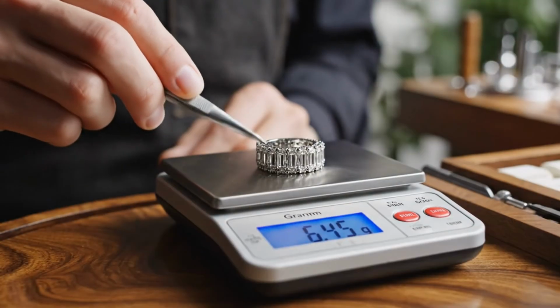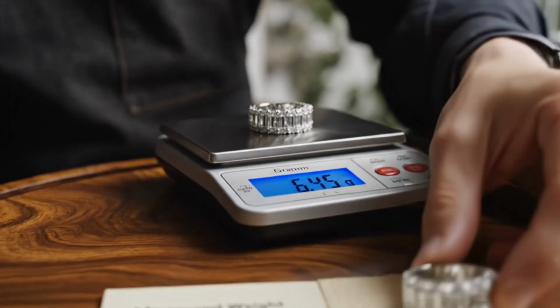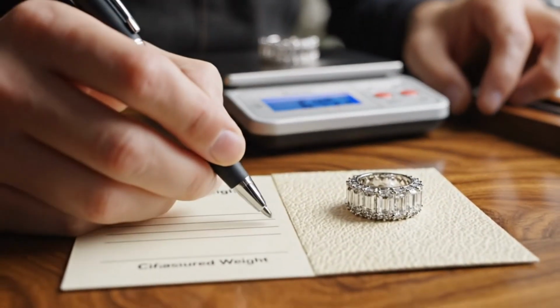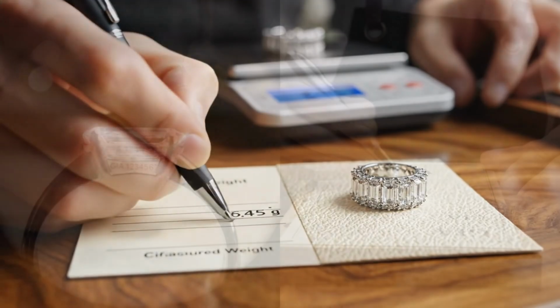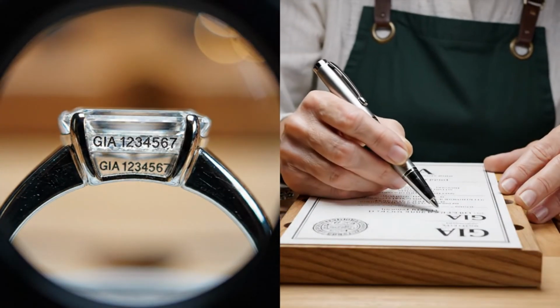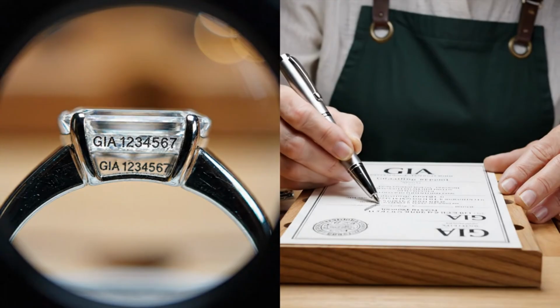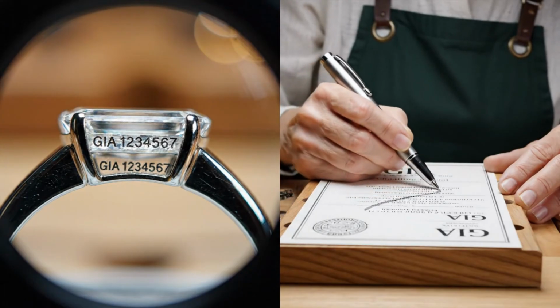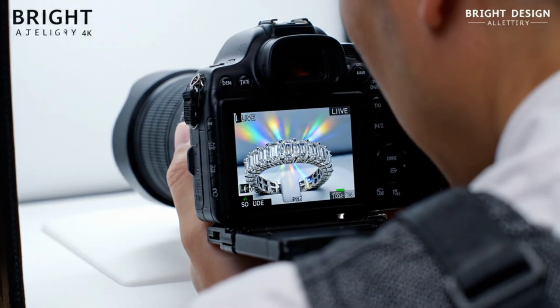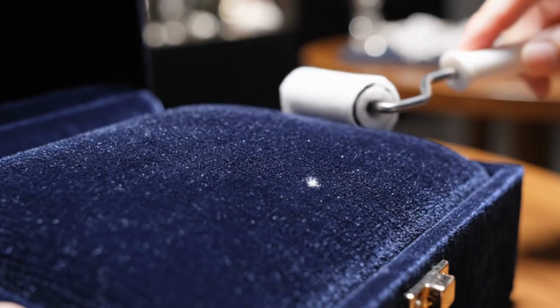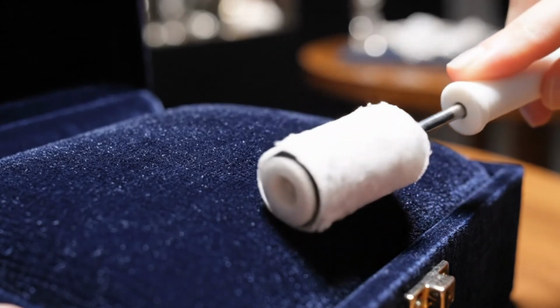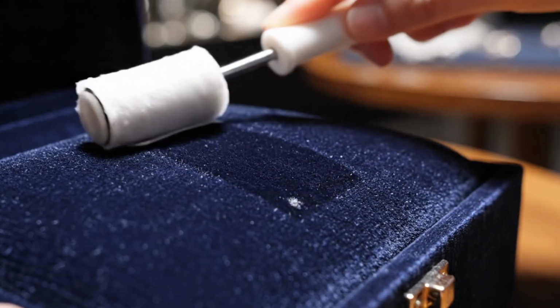The total weight of the finished piece is recorded, confirming the amount of platinum used matches the estimated loss calculations from the casting. We gather the individual grading reports for the diamonds, cross-referencing the laser inscriptions on the stones with the paperwork for absolute certainty today. The ring is placed inside the light box for photography, capturing the brilliance of the emerald cuts for the client's permanent insurance records. We wipe the jewelry box interior with a lint roller, removing even the smallest dust specks from the dark navy velvet cushion material.